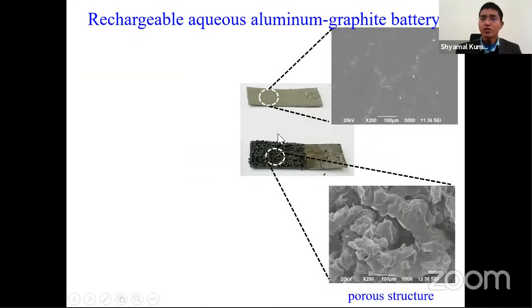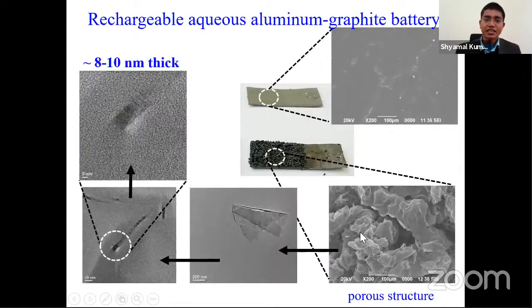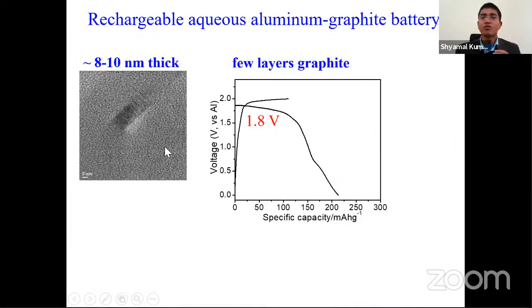Microscopically, when we looked at it, we observed that this graphite foam is very porous, and it is filled with some kind of flakes. With transmission electron microscopy, we proved that these are really nanoflakes, and the thickness of one flake is of the order of 8 to 10 nanometer. And with this graphite foam, when we performed the experiment, we could achieve 1.8 volt, and we could achieve very high storage capacities.